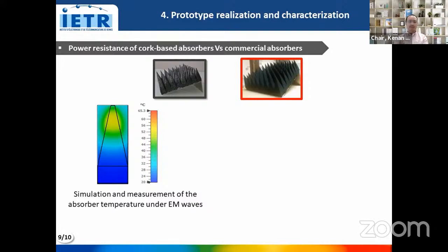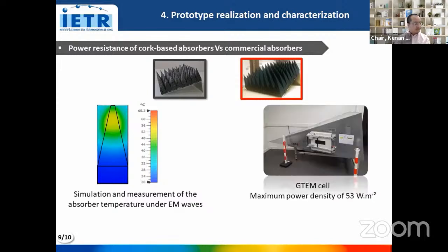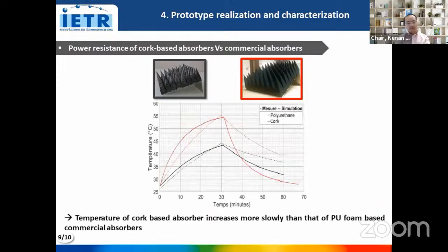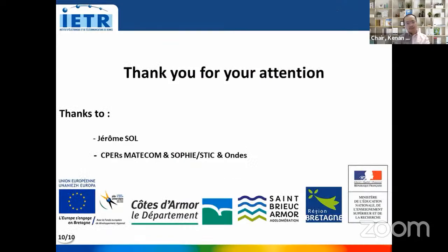Simulation and measurement of the absorber temperature under electromagnetic wave incidence were also done. Here the measurement is done in a GTEM cell under power density of 53 watt per meter square. And this result shows that the temperature of our cork-based prototype increases more slowly than that of the PU foam-based commercial absorber, which predicts a better power resistance for our absorber. Thank you for your attention.